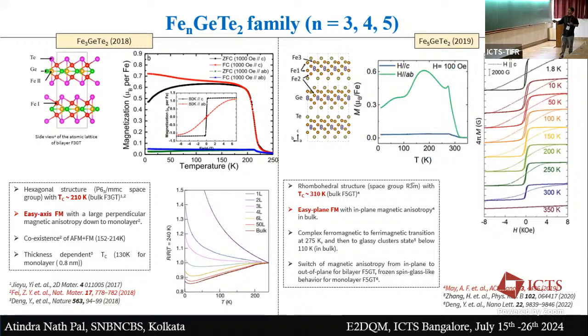Okay, so till now what has been understood is that it's an easy plane ferromagnet, like the easy axis is in plane, and people have observed a complex ferromagnetic to ferrimagnetic kind of transition at around 275 Kelvin, and also a glassy cluster state below 110 Kelvin. They also observed a switch of magnetic anisotropy from in plane to out of plane in the bilayer F5GT system. So it's a frozen spin glass like behavior in a monolayer F5GT system.